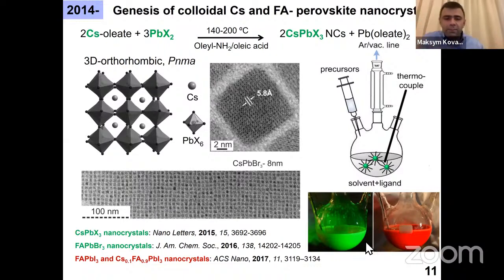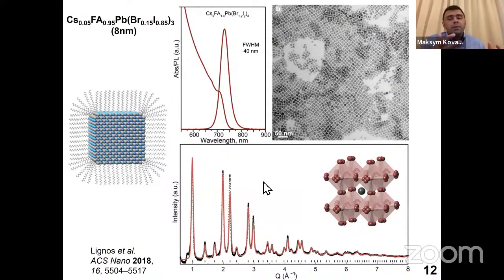And what was super exciting back then, that as you produce them, they emit very bright light. So you don't need to overcoat them with any other semiconductor. They are bright emitters because apparently their surfaces are relatively benign, as they don't introduce mid-gap states. So that is the first example of wideband gap semiconductors whose surfaces are relatively benign with respect to the electronic behavior. So what was also very exciting is to observe that now you can mix different ions and create multinary perovskite nanocrystals, which is that you can mix A site, cesium and formamidinium, or halide, so you can have solid solutions, and therefore you can control the band gap by composition. So you can have phase pure multi-component nanocrystal, which is very difficult to do with chalcogenides, for example.